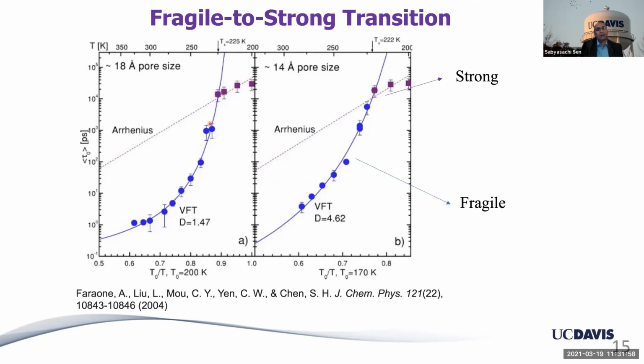Fragile denotes non-Arrhenius behavior. Strong is the Arrhenius behavior. It has nothing to do with the mechanical strength or fragility. But this fragile to strong transition was believed to be happening in a homogeneous body of water inside a nanopore. But now we have a natural explanation of this, where we are saying that this layer by layer freezing gives a natural explanation. Here, the water freezes and the remainder of the water, which is mobile, you are getting the signal from that. So this is the water, not the ice signal.